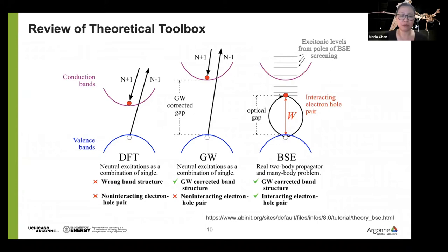Excited states are basically off in DFT, as well as lacking electron-hole interaction. There's a one-more-step approximation beyond DFT in many-body perturbation theory called GW, which accounts for the screened Coulomb interaction between electrons, giving a correct band structure. However, it still does not account for the electron-hole pair. That's why we need an additional level of approximation called the Bethe-Salpeter equation, or BSE, which accounts for the electron-hole interaction using the GW-corrected band structure — and that level of approximation gives us usually pretty good XANES.